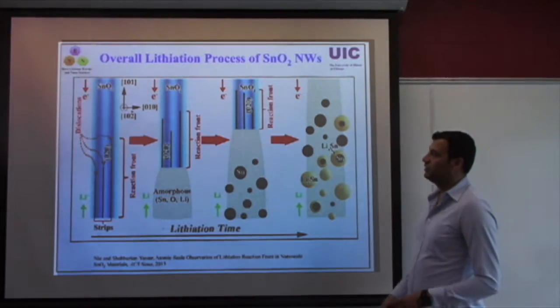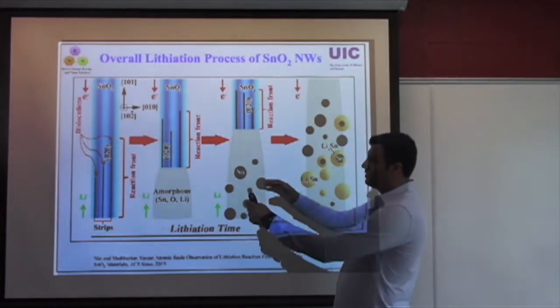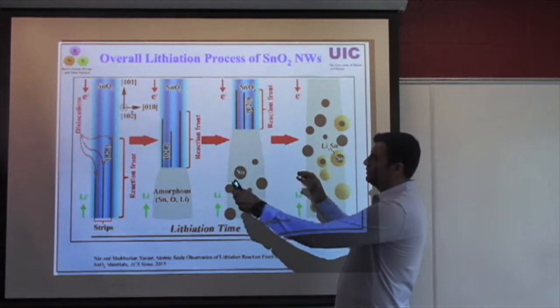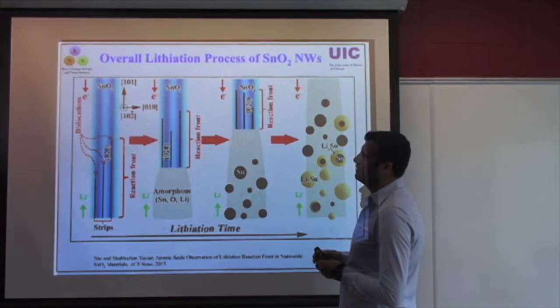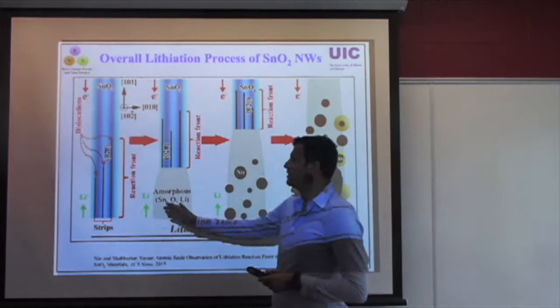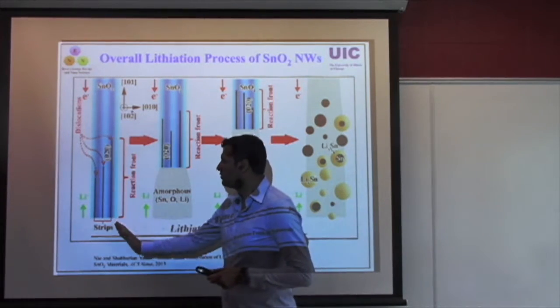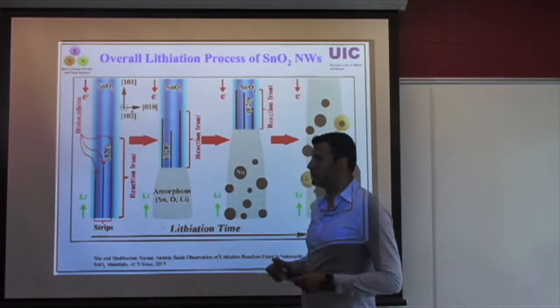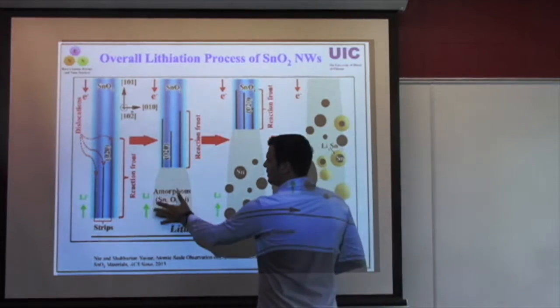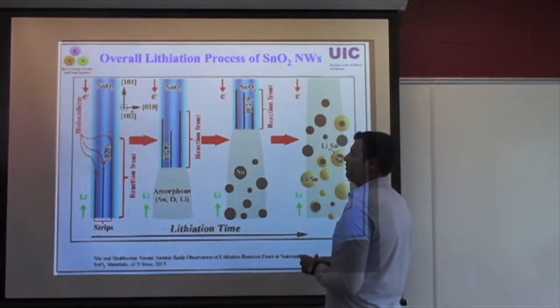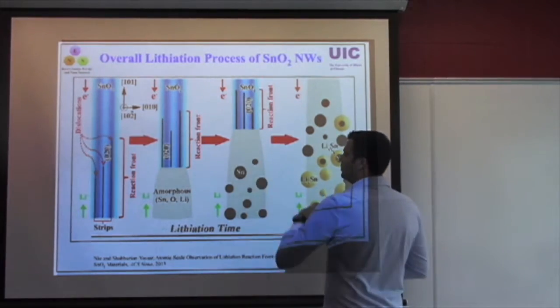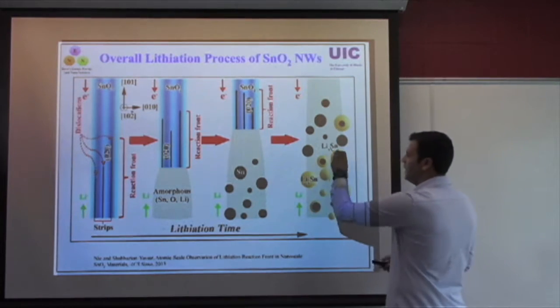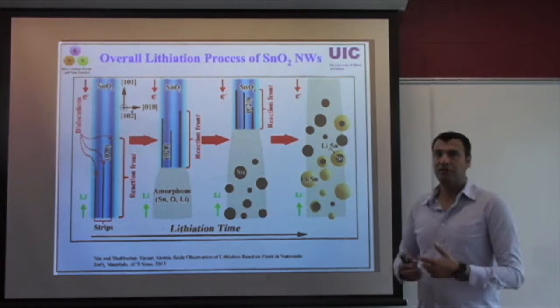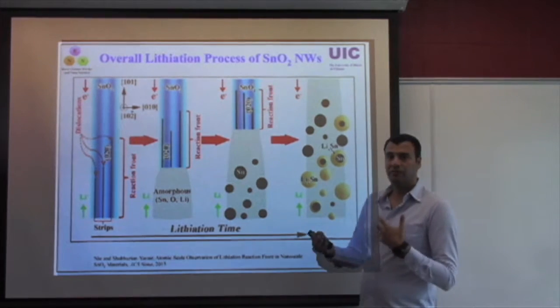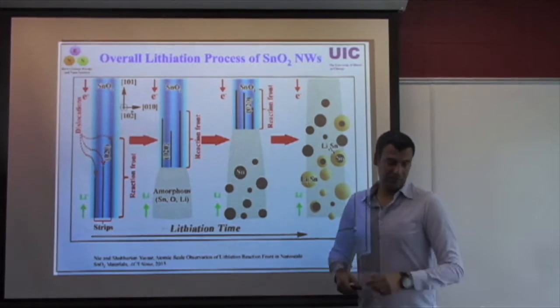So we can make a summary of all this reaction that is happening, and provide a full story of how lithium is transporting through a sample, how the amorphization happened, how the conversion to tin happened, and then how the alloying reaction happened. So we can get the full picture by looking at the in situ dynamics of this electrochemical behavior.